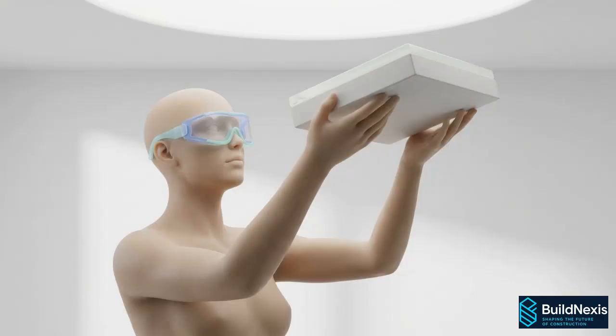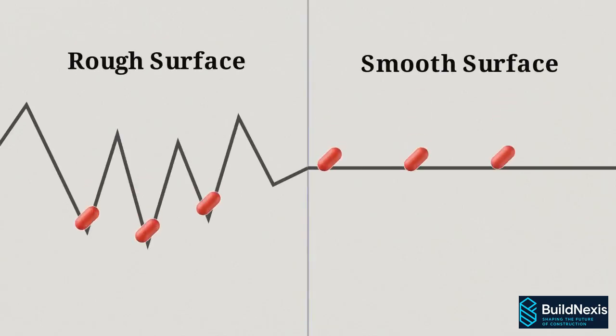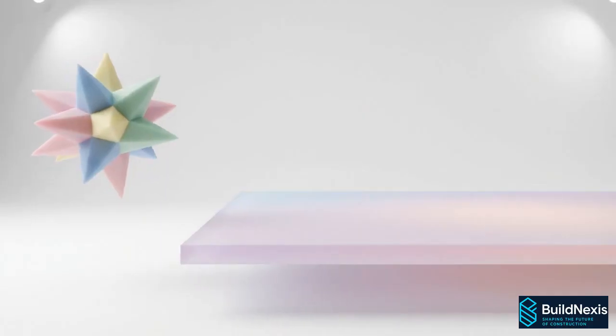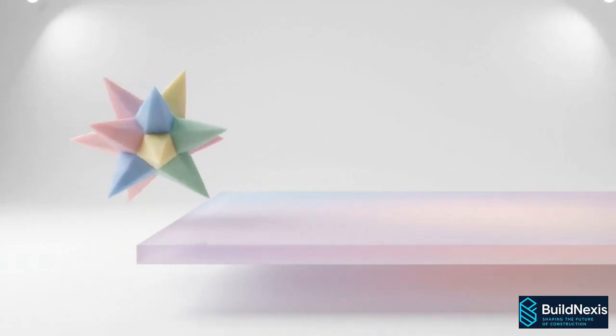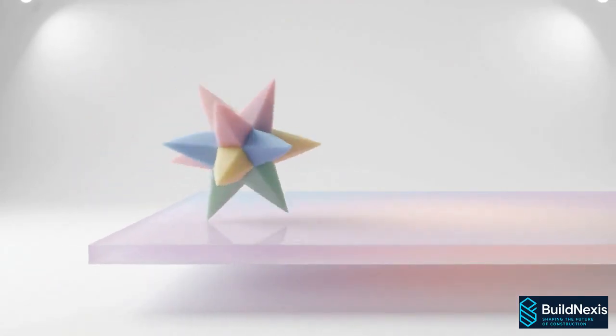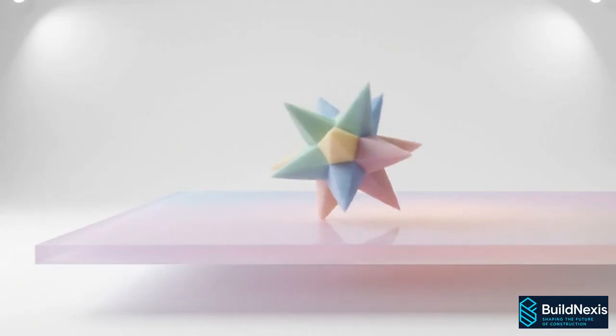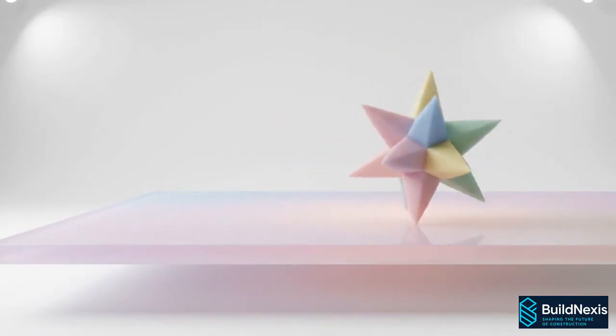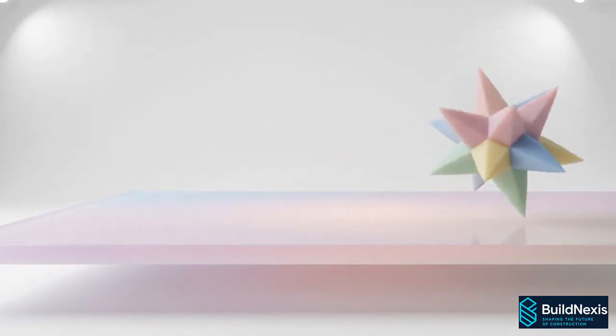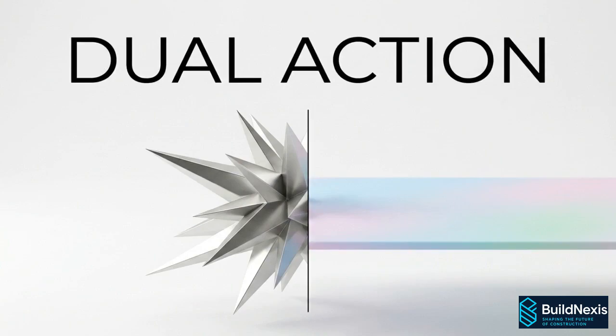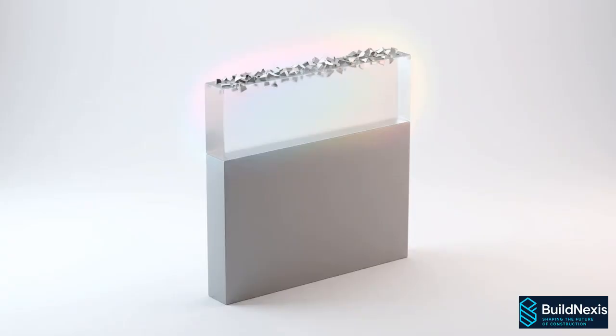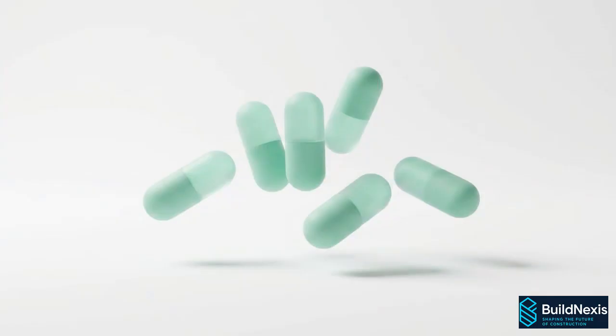But the researchers uncovered a second factor in the tile's performance. The physical shape of the tile is just as important as the chemicals coating it. It comes down to surface topography. A smoother glaze physically repels bacteria, denying them the microscopic footholds and crevices they need to attach and multiply. True antibacterial power requires a two-front defense. It requires low-heat chemistry to preserve the silver, and an ultra-smooth physical surface to deny the enemy a landing zone.